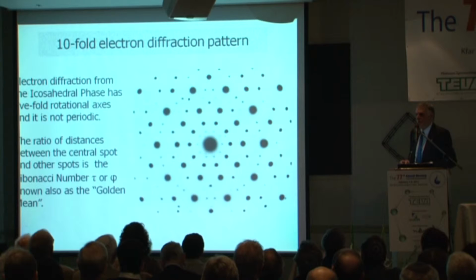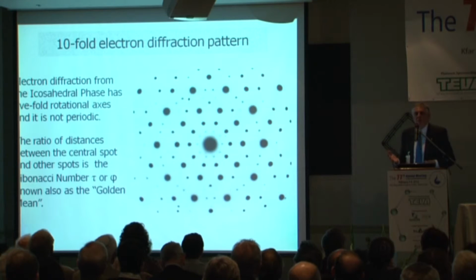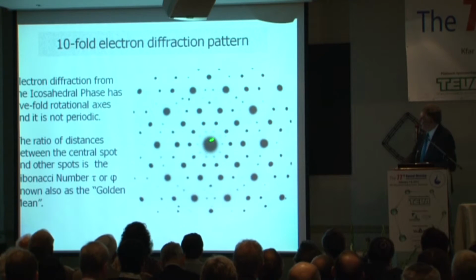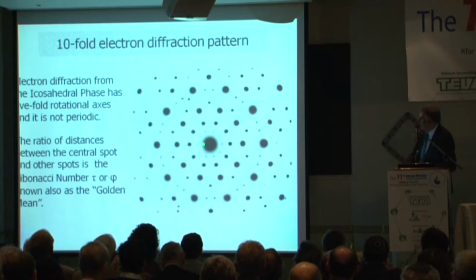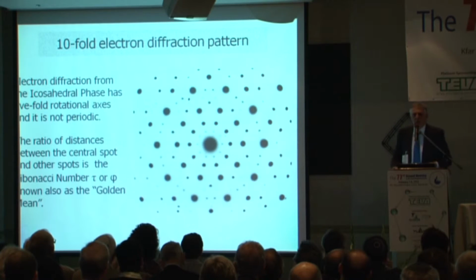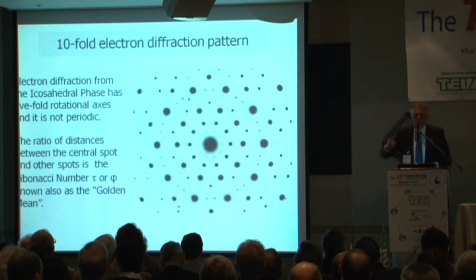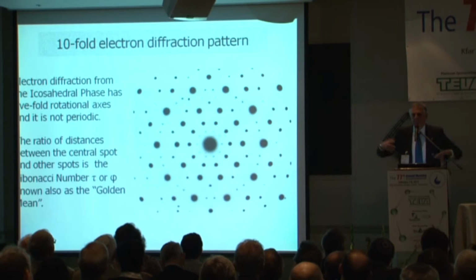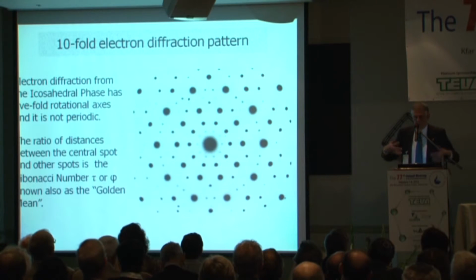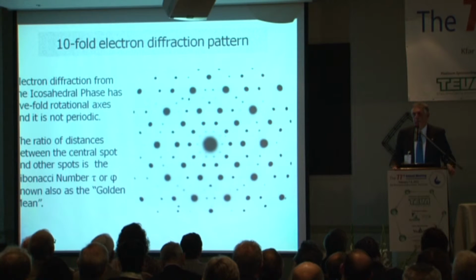The other thing, which is strange here, is that there is no periodicity. You see, if you take the distance from here to here, and you multiply it by 2, or any other integer, you get here. And there is no intensity here. There is no spot here. If you take this distance multiplied by 2, you arrive here. And there is nothing there. No periodicity, 10 or 5-fold rotational symmetry. Very strange. But based on my previous experience, I decided that what it can be is a twinned crystal.